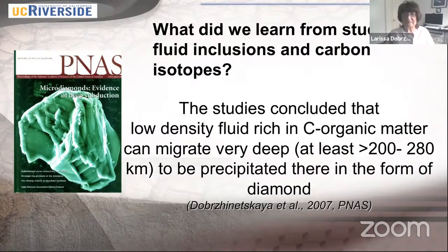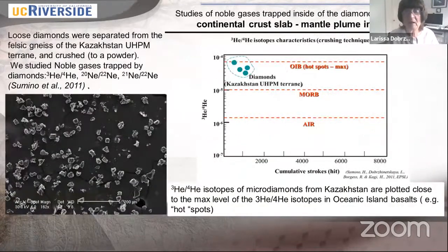What did we learn from the study of fluid inclusions and carbon isotopes? Yes, the summary says that the study concluded that low density fluid rich in carbon organic matter can migrate very deep during subduction of the material, at least to depths of 200, 280 kilometers, where it is precipitated in the form of diamond. So then we started to study noble gas isotopes.